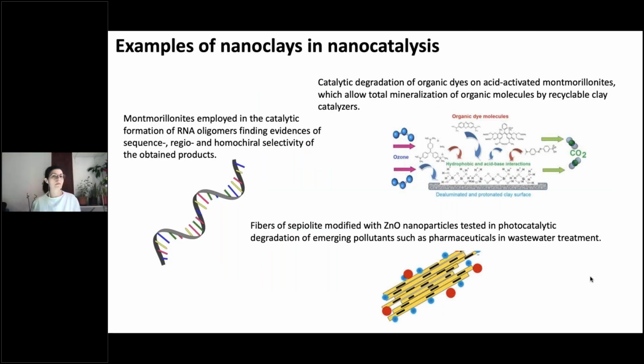Here, there are some examples of nanoclays used in nanocatalysis. For example, the catalytic degradation of organic dyes on acid-activated montmorillonites, which allow total mineralization of organic molecules by recyclable clay catalyzers. Then montmorillonites employed in catalytic formation of RNA oligomers, finding evidences of sequence, regio, and homochiral selectivity of the obtained products. And then fibers of sepiolites modified with zinc oxide nanoparticles tested in photocatalytic degradation of emerging pollutants, such as pharmaceuticals in wastewater treatment.